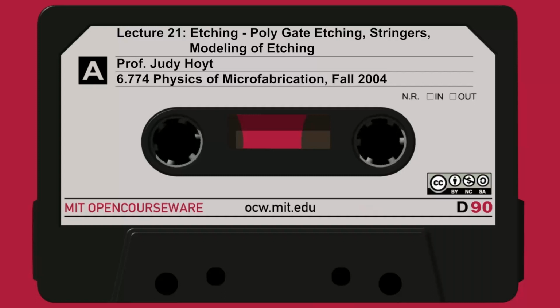What do I have to do in this process? After you put the gate down, you have to implant the source drains and you have to anneal them, typically at 1,000 degrees these days, for 10 seconds, or 1050. There aren't too many metals you can take up to 1050 and not melt them. Most metals will melt, or if you don't melt them, they could undergo dramatic phase transformations. Some of them could diffuse into the wafer and cause problems with deep levels. So metals are not considered very good to have at high temperatures.